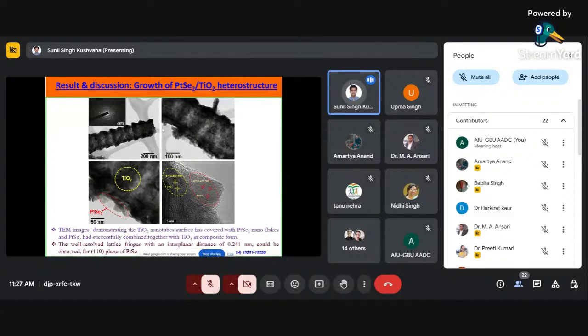And of course, when we are going more details, like to really see the atomic scale images or to see the process really happening, we have this technique that is called the transmission electron microscopy. So in the transmission electron microscopy, of course, we have the very thin structure of only few nanometer or few hundred nanometer structures we can measure. And after that, we can zoom even to the atomic scale image, even up to 5 nanometer, 10 nanometer area. And then from here, we can see what kind of crystal structure. So again, here we can see this is the TiO2, and then top of this, it is PtSe2 formation. So that is the one of the technique. Of course, it requires some dedicated sample preparation, which is very difficult for the TiO2, and also of course it is destructive process.